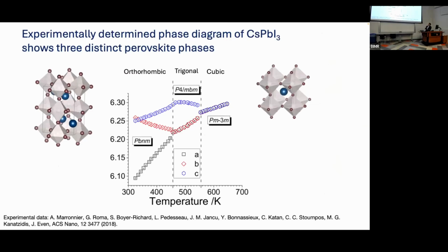In addition to the possibility of different phases for these perovskites, it's also necessary to understand the evolution of the phase as a function of temperature. DFT calculations are performed at 0 Kelvin, way over here. But in reality, experimentally, what's been observed is that these materials can adopt different phases over different temperatures. In this case, the y-axis is the lattice parameters. On the far left side, at about 300 Kelvin, there are two that are almost similar and one that's very much smaller. So it's something like this orthorhombic phase. As you heat the system, eventually all the lattice parameters look very similar, so it adopts this cubic phase. You'll find this in the literature for these compounds, that there's this evolution of the phase as a function of temperature. And so ideally, if we're going to screen the compounds, we'd not only be able to take in realistic structures, but would also be able to account for the phase diversity over different temperatures.